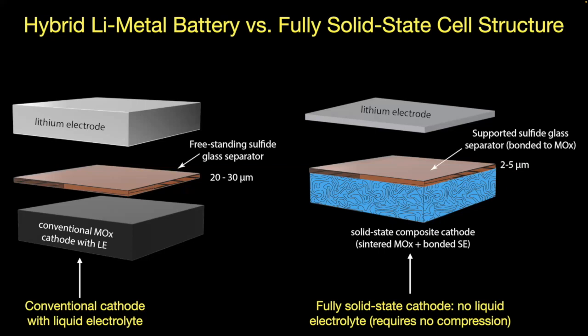This is all bonded. And because we're bonding glass to a rigid composite cathode, we should be able to go even thinner. So we think we can probably move to 2 to 5 microns of glass. That'll take us, of course, to higher energy density. The same type of approach has been done in solid oxide fuel cells, where you use nickel YSZ composites and then lay down YSZ on top. And we in the past have done 2 microns of pinhole-free material. So it's certainly doable.